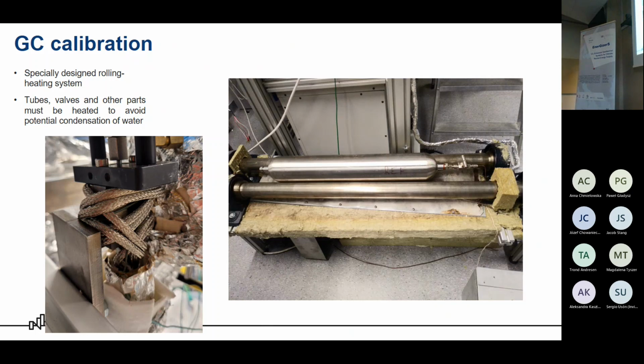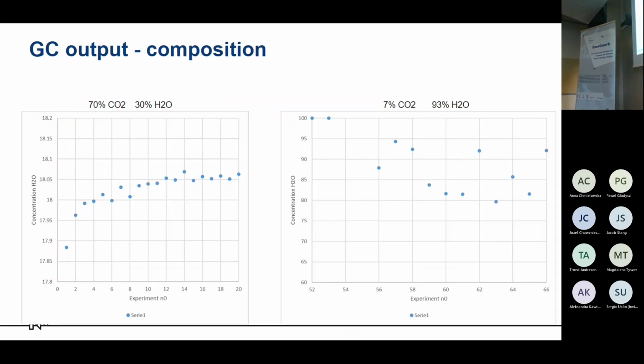So rolling and heating is for evaporating the water and to reach the uniform mixture. And tubes, valves, and other parts must be heated to avoid potential condensation of water. It is really important to have the uniform mixture without any water that can condense. And here is the output from the GC, and for the mixture of 70% of CO2, we have very stable results. So for this mixture, everything is okay.